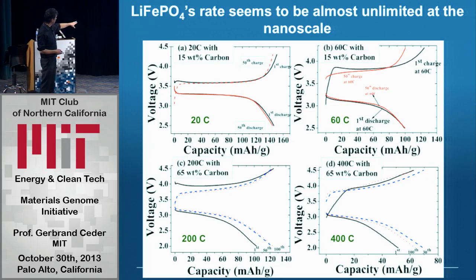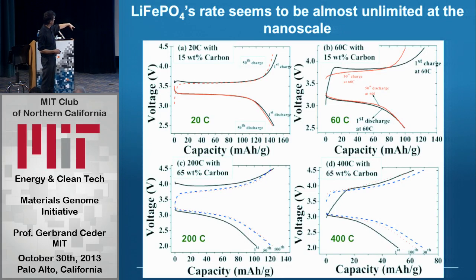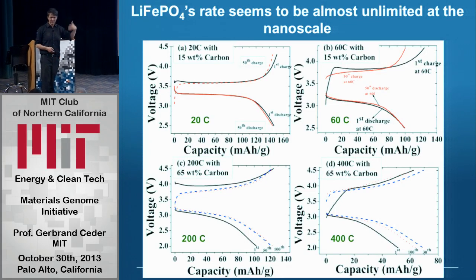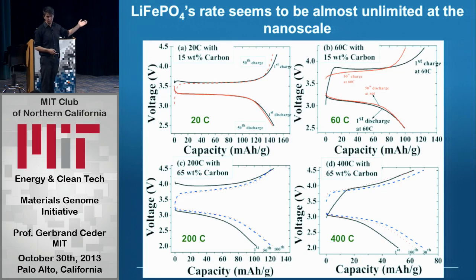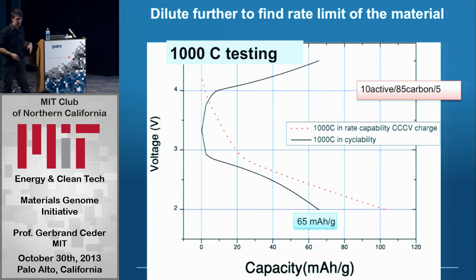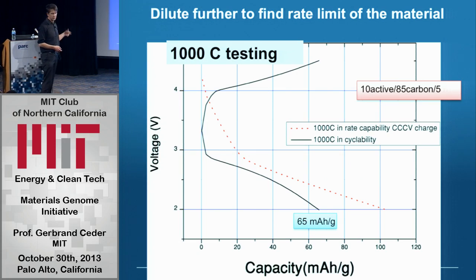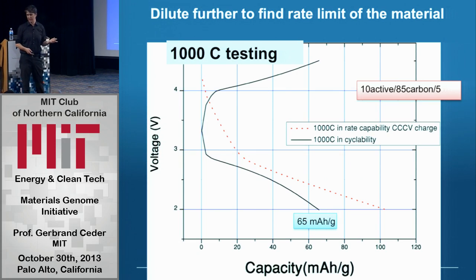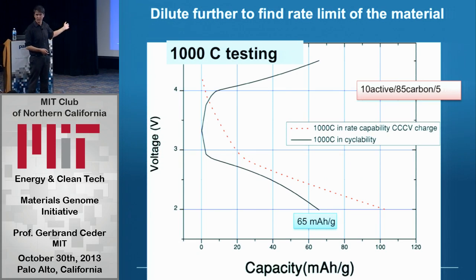These C rates here are not temperatures. A C rate of 10 C means you can do 10 charges or discharges per hour. So 400 C means that you could, in principle, do 400 cycles per hour, which is really one per 9 seconds or something like that, right? We now did 1,000 C. You start losing capacity. This is essentially a charge-discharge pulse that charges the electrode about a third of the way in 3 seconds, right?